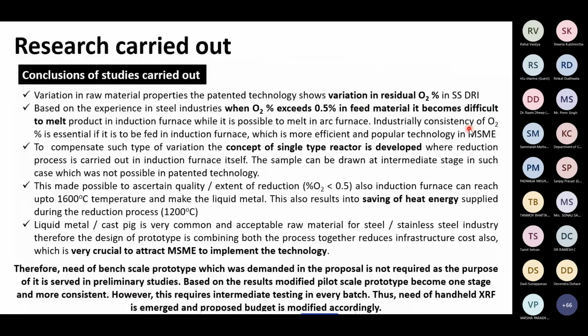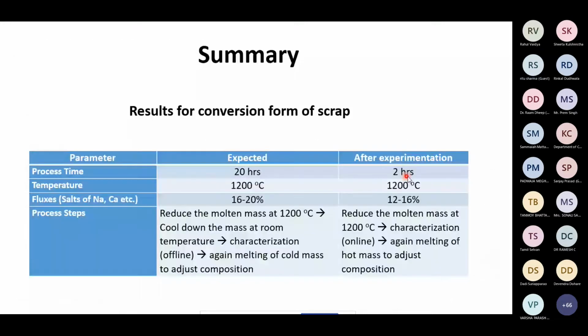So what we expect, as the research is still going on, is that process time instead of 20 hours is reduced to 2 hours. Temperature 1200 remains the same, and the fluxes that we are going to add also get reduced. But the time, which is 20 hours in a two-step process, we are under research with the collaborative industry to reduce into 2 hours. So the time is also saved. You can understand, 1200 degrees centigrade for 20 hours versus 1200 centigrade for 2 hours, how much energy is also saved. And finally, we are going to get a good metal compound that is directly recycled. So that research is going on. Hope to get the research results soon, in the coming 6 to 8 months.